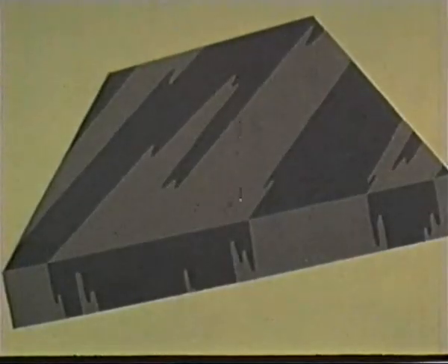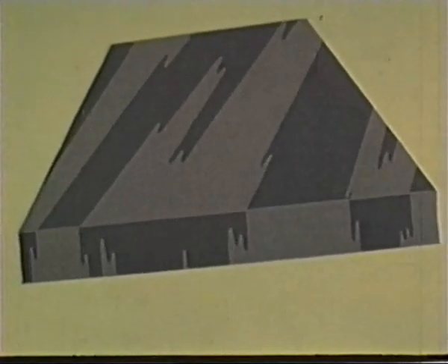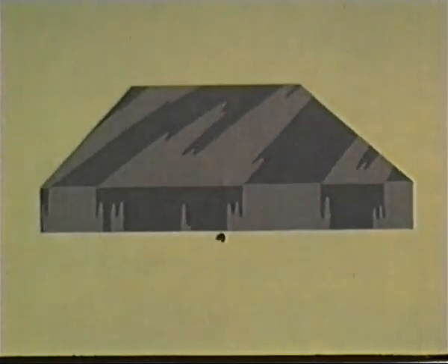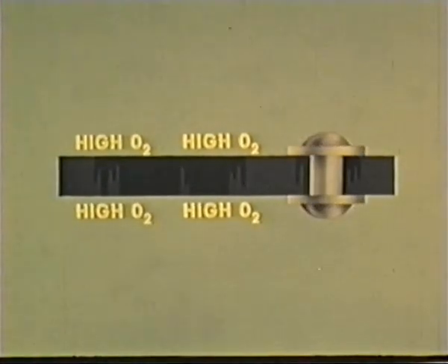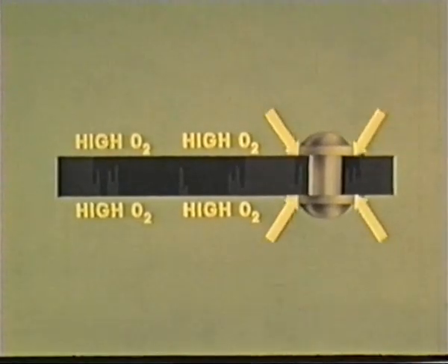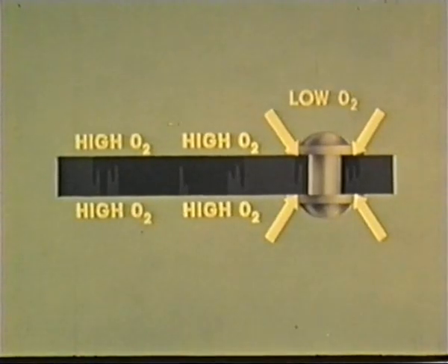A difference in potential will occur when active and passive areas develop on the same piece of stainless steel. For example, the passivity of stainless steel depends upon a protective film of oxide, which while not visible is nevertheless very real. However, the amount of oxygen in the environment affects the stability of this film. The stability is also greatly reduced in the presence of chloride ions and high concentrations of hydrogen ions.